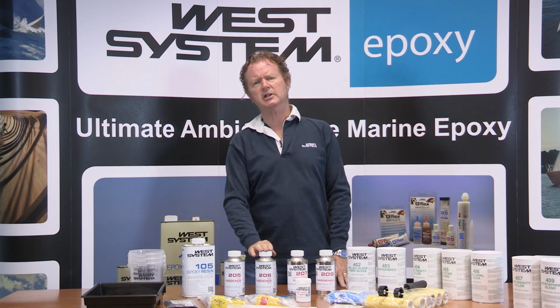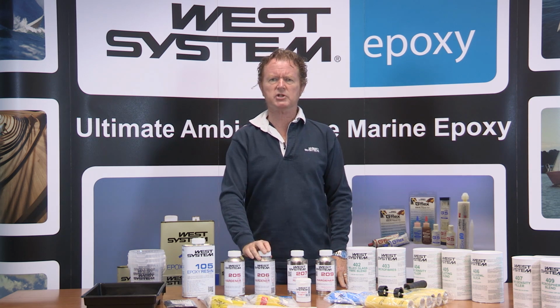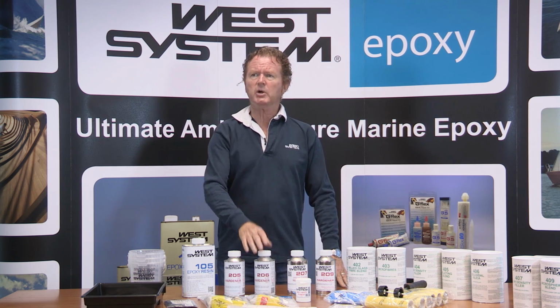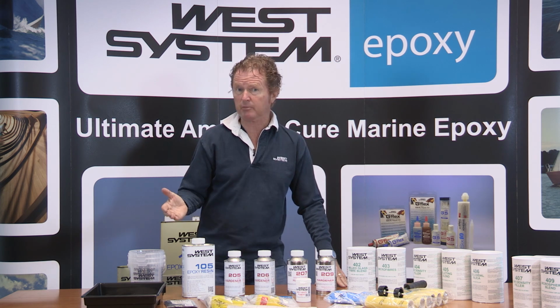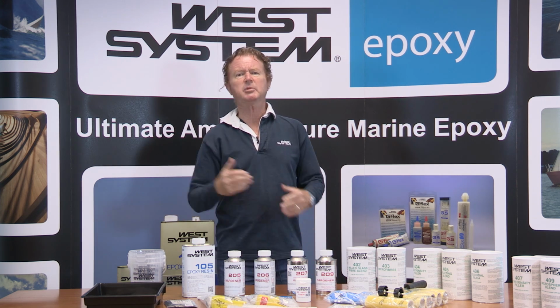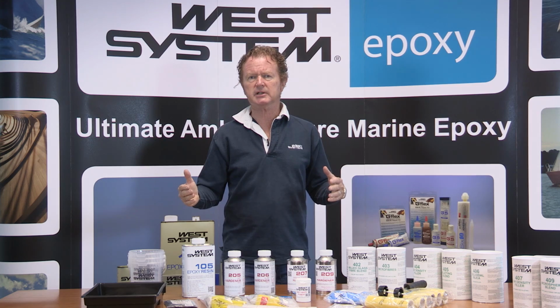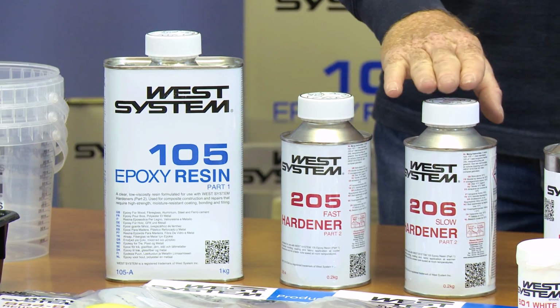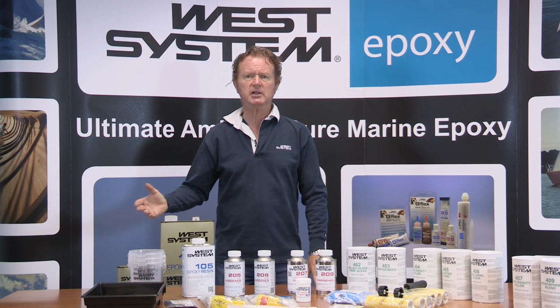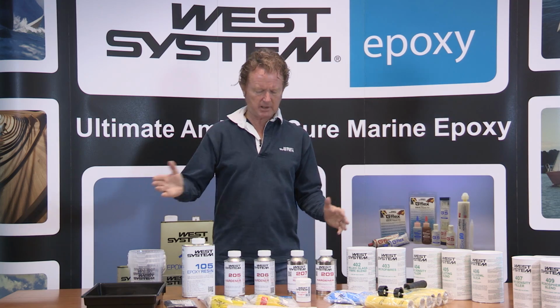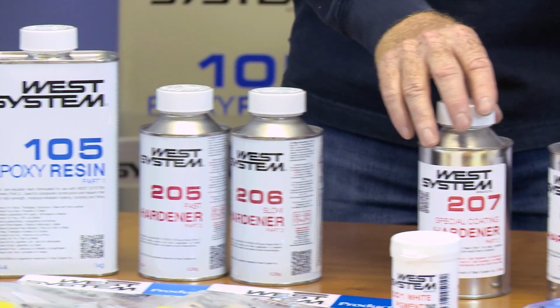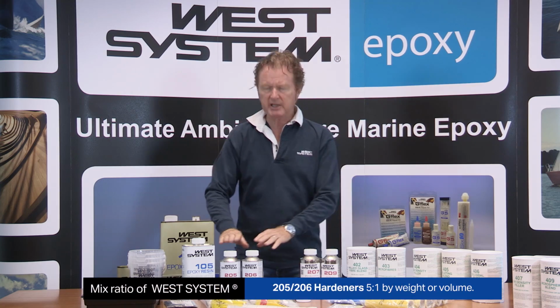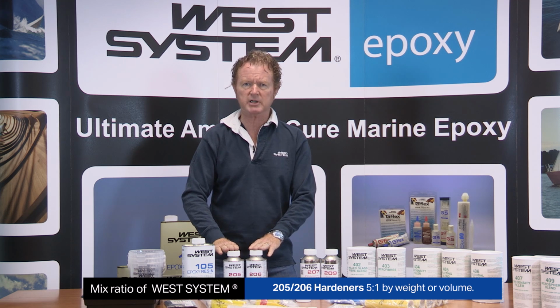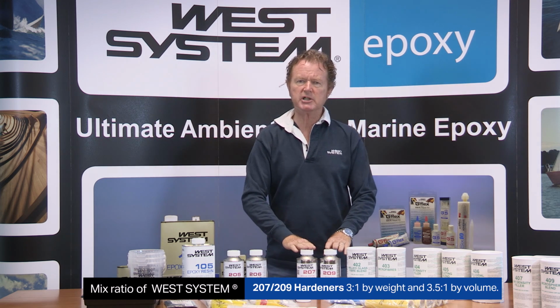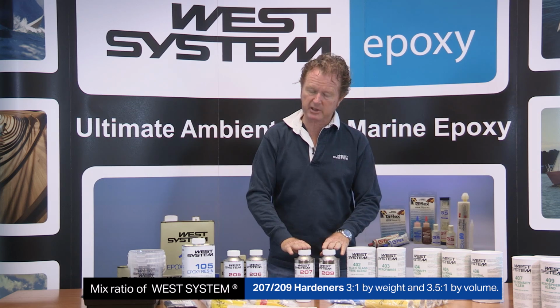Our 206 hardener, we sell more of this to warmer countries, maybe in the Mediterranean, where you need 20 to 30 minutes of pot life and you're working in maybe above 16°C. This is the product that we'll sell to the south of France or Spain or anywhere in the Mediterranean. These are different to the other two specialist hardeners in as much as these are a 5-to-1 ratio. And these specialist hardeners are a 3-to-1 ratio.